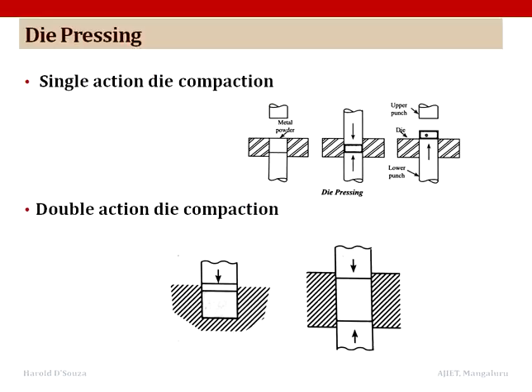Die pressing. The metal powders are placed in a die cavity and compressed to form a component shaped to the contour of the die. Now, the pressure that is used for producing green compact of the component varies from 80 megapascal to around 1400 megapascal. Depending upon the material and the characteristics of the powder used, mechanical presses are used for compacting objects at low pressure. Hydraulic presses are for compacting objects at a higher pressure.